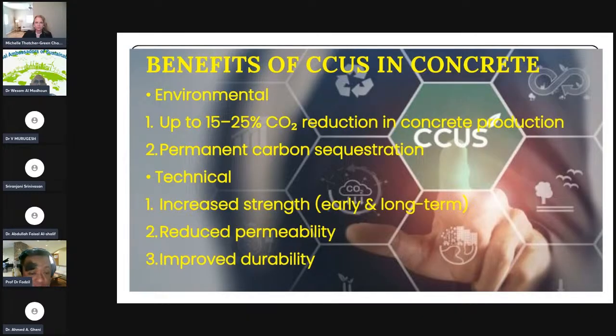So from all the research being carried out, what I can say is that the benefit of CCUS in concrete is especially on the environment, where there is up to 15 to 25% CO2 reduction in concrete productions. The permanent carbon sequestration also becomes a benefit to the environment, because the CO2 has been successfully cured or stored in the concrete. On the technical part, the utilizations of CO2 have increased the strength of concrete early and long term as well, reduce the permeability and improve the durability of concrete.